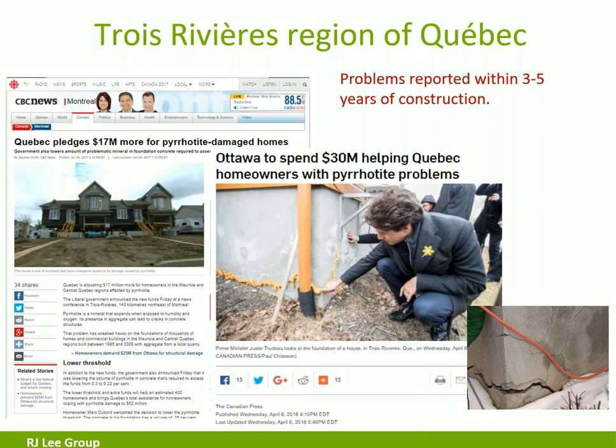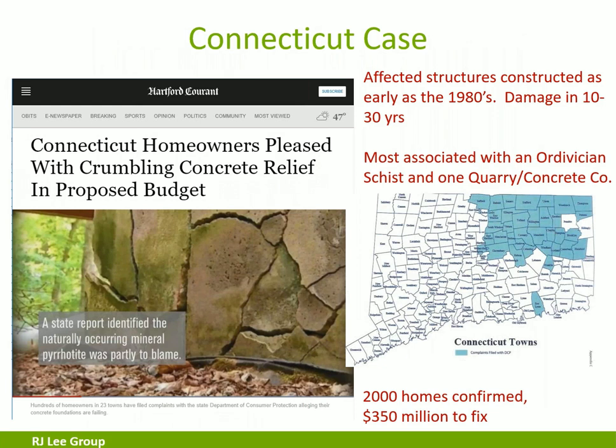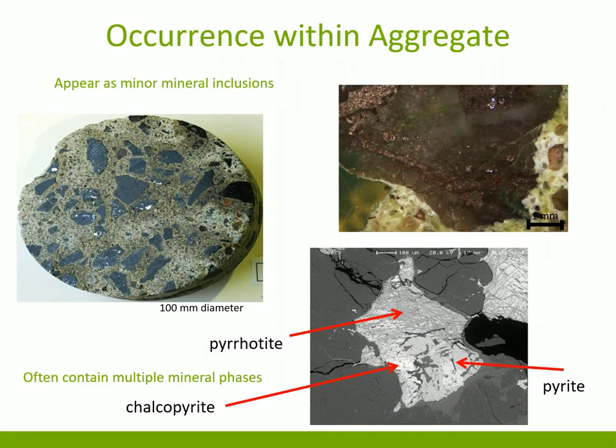So just to give you an idea of some of the difficulties with this. These minerals are present in very small amounts. There has been evidence of some of this damage showing up in the Quebec aggregate when you only have 0.2 or 0.3% by volume of pyrrhotite in the aggregate. If you look at these images, the one on the left is a 4-inch diameter core slice, and those little bright particles inside the aggregate, those are the pyrrhotite. A lot of times we'll see that it is present with a lot of mineral phases. So pyrite, pyrrhotite, chalcopyrite, they often are found together.